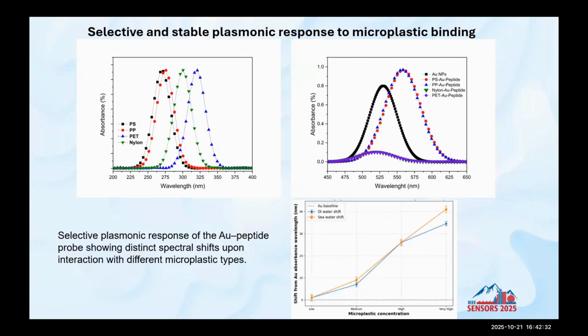Also, we tried to see how selective this technique could be, because the whole peptide design, as I told you, was specifically for PS and PP. We exposed it to PET and nylon, other common types of plastic in water sources. We saw that, as shown here, they only show the shift for polystyrene and PP, not PET and nylon. So the peptides are selectively designed to bind to those types of plastic.